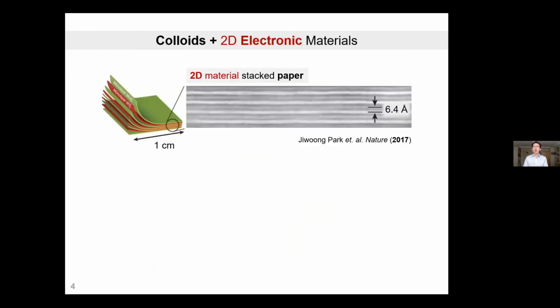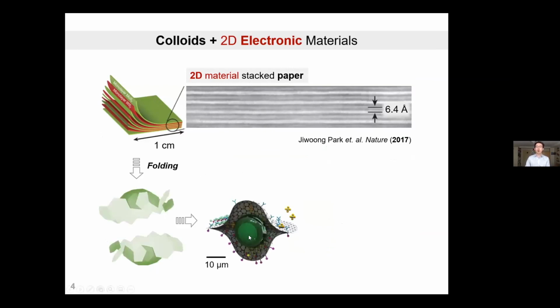If you take a layer of two-dimensional material, or a circuit that you can pre-pattern out of a two-dimensional material, and treat them as origami papers, and if you fold them around an already existing dumb colloidal particle, you can have the top and bottom layer fold around this particle. And if you have a way to cut these 2D materials around the edge of the particle, then practically you're